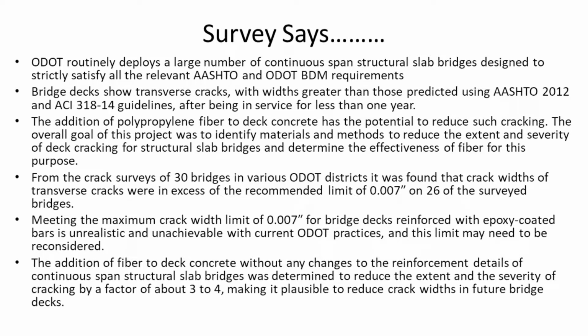Maybe through this study they found that they could improve what they had. The addition of fiber to the deck without any changes of the reinforcement details, which they're using epoxy, continuous span bridges, was found to reduce cracking by a factor of 3 to 4. So pretty significant data, and it was plausible to reduce the crack widths in future bridge decks.